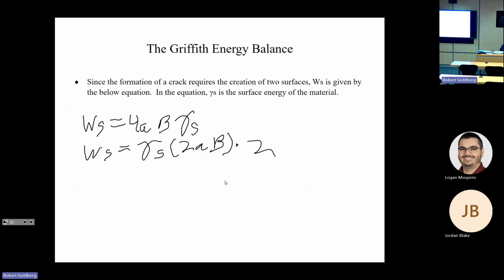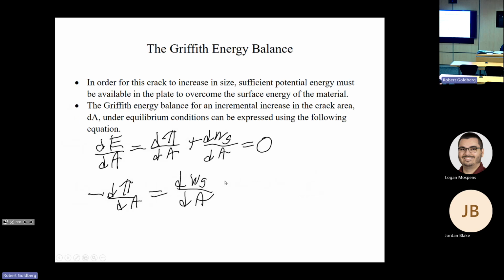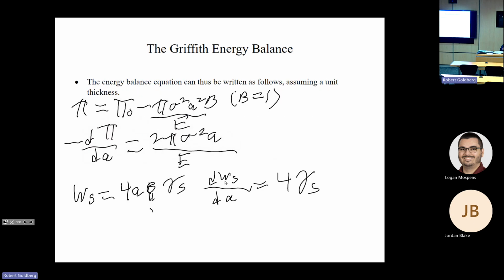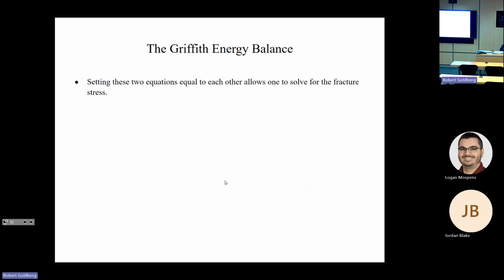So now we'll go back. When we did our quick energy balance discussion, we said that this term has to equal this term. And if it's true for the derivative with respect to the area, it's also true for the derivative with respect to the half crack length. So B is equal to 1. So what we can do is take this term here and set it equal to this term here. And so we have that 2 times pi times sigma squared A over E is equal to 4 times the surface energy, and we'll solve for this fracture stress.